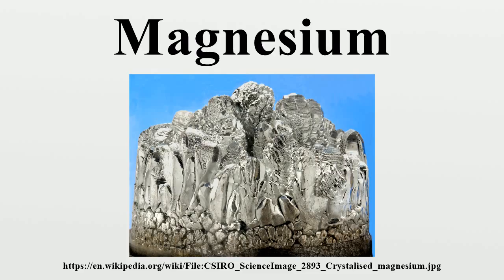Corrosion. The presence of iron, nickel, copper, and cobalt strongly activates corrosion. Reducing the quantity of these metals improves corrosion resistance. Sufficient manganese overcomes the corrosive effects of iron. This requires precise control over composition, increasing costs.